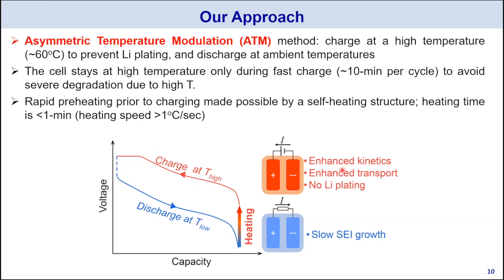So the key here really is to control the time for the battery to be exposed to elevated temperature. But fortunately, this is a 10 minute fast charging, so very short. And technologically, a key element is to find a structure or a way to rapidly heat up the cell. And it has to be done with a heating speed greater than 1 degree per second, or be able to heat up from room temperature to 60 degrees Celsius in less than a minute, right? Because charging time is only 10 minutes. So we have to keep it quick.